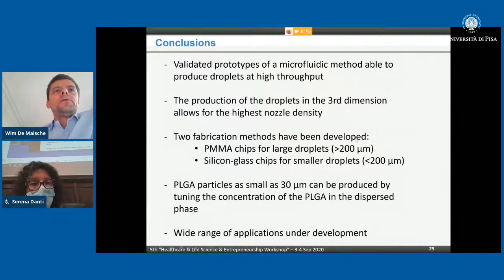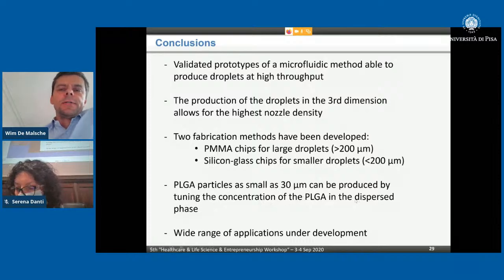All right, so that brings me to my conclusions. We have validated a bunch of prototypes of microfluidic methods able to produce droplets at high throughputs. Production of the droplets in the third dimension allows for the highest nozzle density. This is really critical to go to the tens or even the hundreds of liters per day. We have 2 fabrication methods. For the large particles, we have relatively cheap methods. For the smaller particles, we have more expensive devices, but again, we have high-value products, so this is in the end still quite okay. We can produce PLGA particles down to 30 micron, but we can reduce them by going to silicon, but also by playing with PLGA concentration.